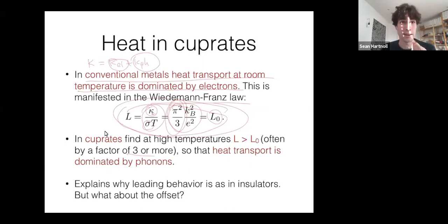Just by the way, experimentally, if you really want to talk about quasi-particles in the Wiedemann-Franz law, the cleanest thing is at zero temperature, because there are no phonons at all. You just go to electrons. The cuprates at the critical doping, where the resistivity is T-linear all the way down to zero temperature, obey the Wiedemann-Franz law with the pi squared over 3. That's an experimental fact, actually. So just T equals 0, p equals p star, the critical doping, the resistivity is some constant plus a term that goes like temperature.